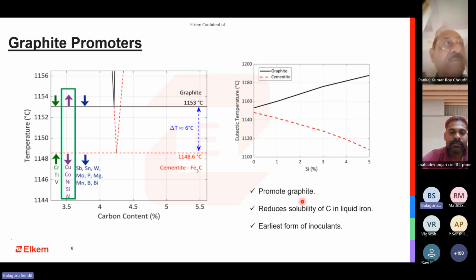So silicon is one of the strongest graphite promoting elements, and it also stabilizes it. So these are elements which actually enlarge the delta T. All other elements will try to make this range close, which is very dangerous. We would like to have this range widened. So graphite promoter elements are elements that we should try to have in our base metal.